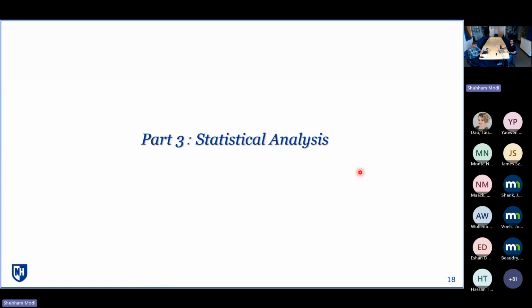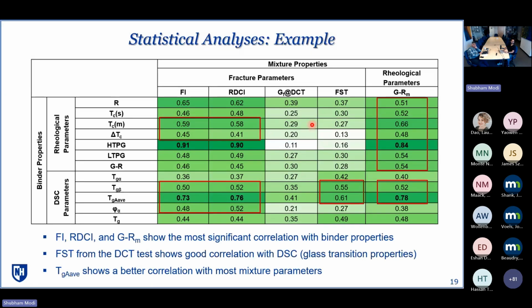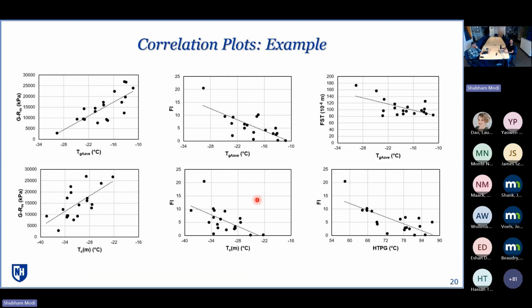Now discussing the statistical analysis and correlations between these mixture properties and binder properties. Binder properties are shown in rows and mixture properties are shown in columns. Here we can observe that the mixture properties at intermediate temperatures, such as FI, RDCI, and Glover-Rowe parameter, had overall better correlations with the binder parameters, rheological especially. On the low temperature side, mixture parameters such as FST have shown comparatively good correlation with the DSC parameter than the rheological parameters. And TGAV parameter has shown good correlation with all the mixture properties. And these are some example plots of the good correlation that were shown previously.